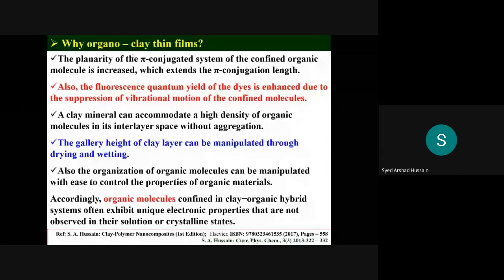A clay mineral can accommodate a large number of organic molecules in its interlayer space without aggregation. Also, what you can do, you can play with the gallery height, the height of the space between the clay layers, by manipulating the environment. Also, one can control the organization of the incorporated material by manipulating the environment. Accordingly, organic molecules confined in clay organic hybrid systems exhibit unique electronic properties that are not observed in their solution or crystalline states.